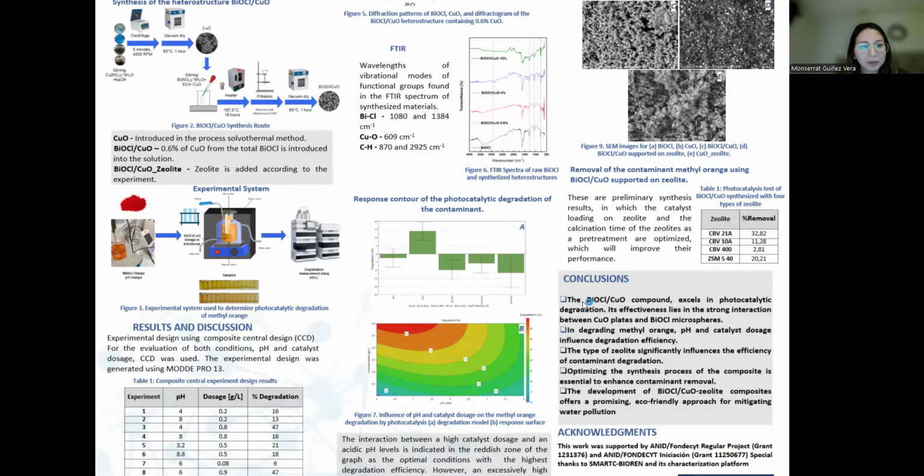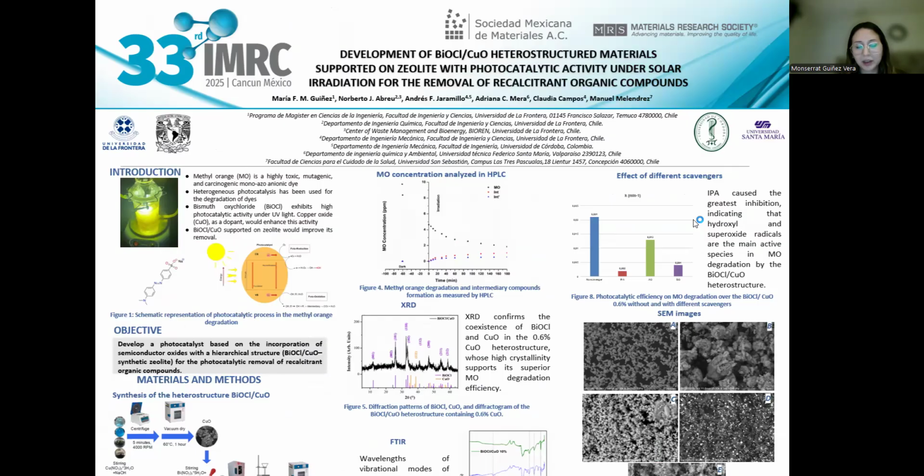And also, we have that excessive dosage decreased performance, likely due to particle agglomeration or light scattering. The scavenger test identified hydroxyl and superoxide radicals as the main active species. Regarding the zeolite type,